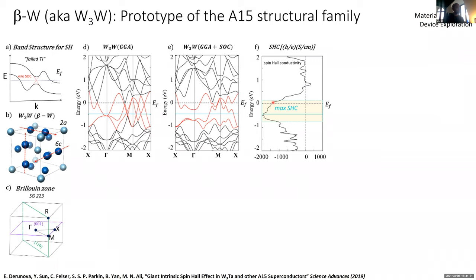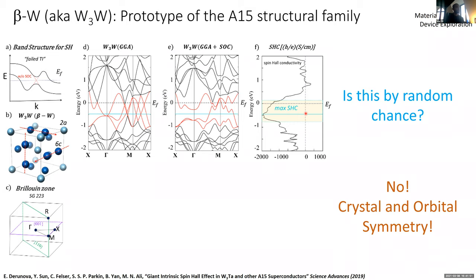And if you calculate the spin Hall conductivity as a function of energy, pretty much exactly where you'd expect, at the level that crosses the equivalence point of as many of those crossings as possible, you end up with a peak in the spin Hall effect. So it was coming not by random chance, of course, but by the crystalline orbital symmetry effects that we talked about earlier. So what we said was, okay, now that we understand that, if symmetry is the driver, then other compounds that have the same crystallographic structure and similar orbital symmetries are definitely going to show the same effects. It's a matter of a filling factor.